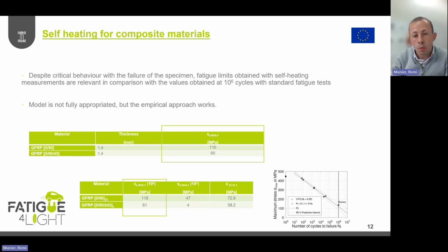but here for composite materials, as we can deal with the weakest link theory, when we know that when one fiber breaks, it will cause the failure of the entire specimen, and that's what's occurring here, with a limitation of the value. So we can have good results for one orientation of the fiber. For the other one, there was an increased error, but we can say that this method, as a first attempt, was quite relevant also for composite materials.